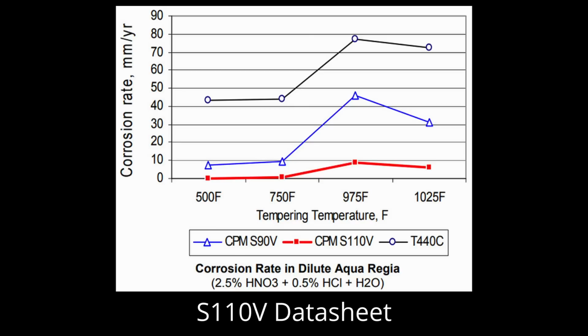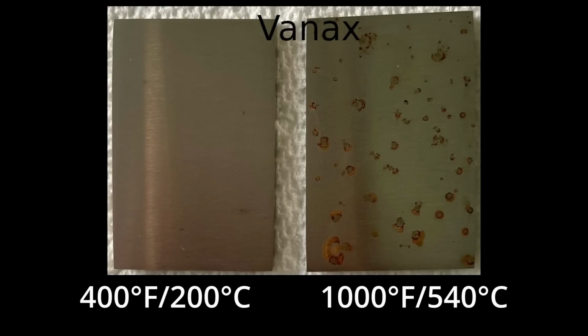In my testing of Vanax, comparing a 400 degree Fahrenheit temper and a 1000 degree Fahrenheit temper, I sprayed it with 1% salt water. The high tempering temperature Vanax corroded. I got rust spots all over it, where the low temperature tempering Vanax was completely clean. So it turned the Vanax from a super high corrosion resistant steel into something that behaves more like your average stainless steel.